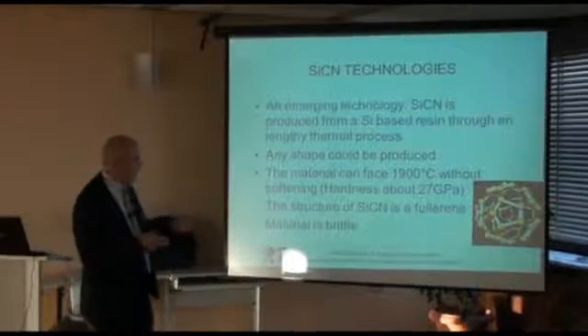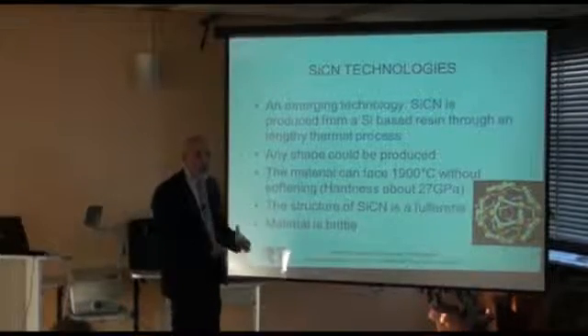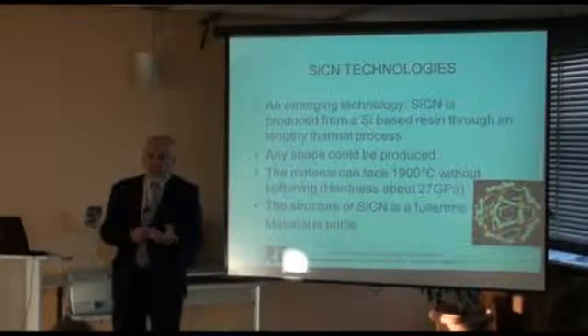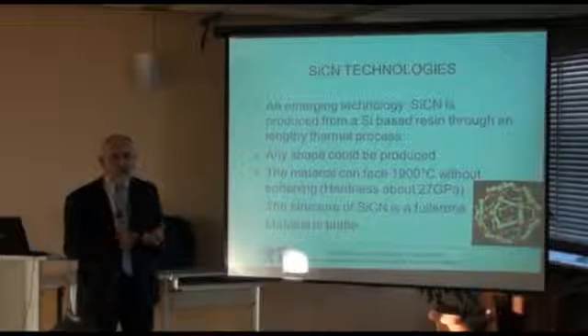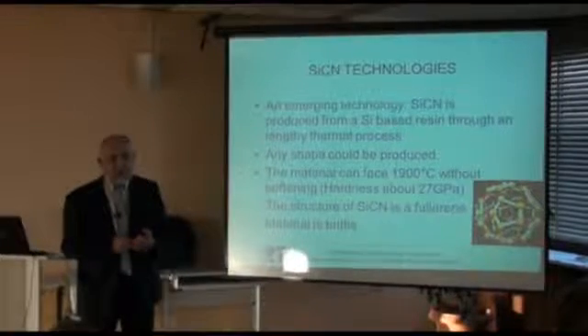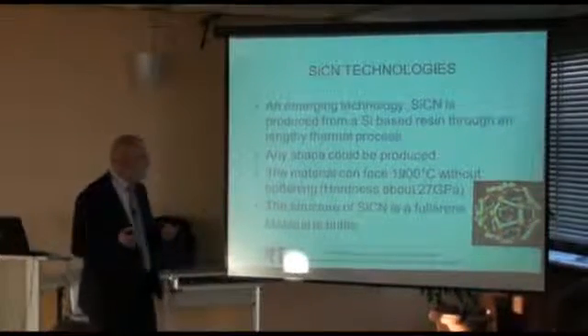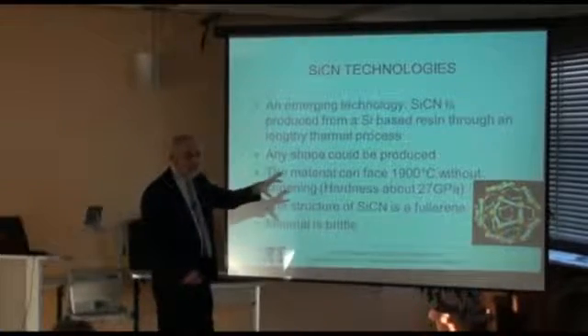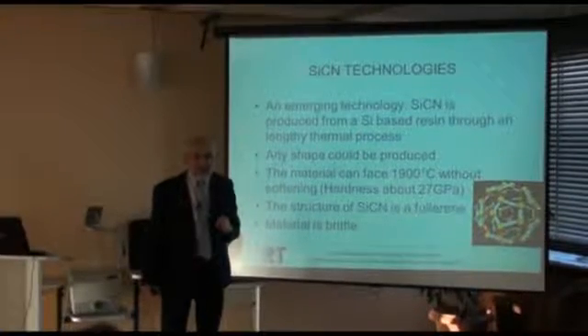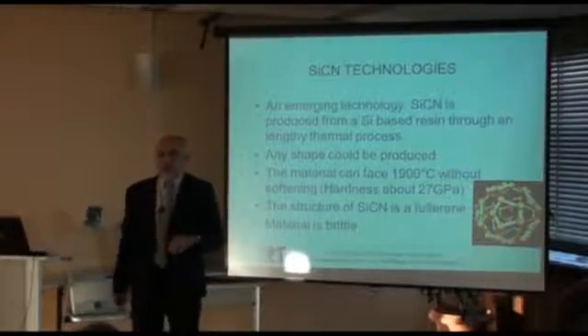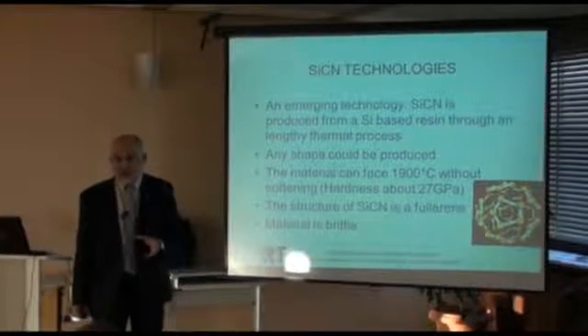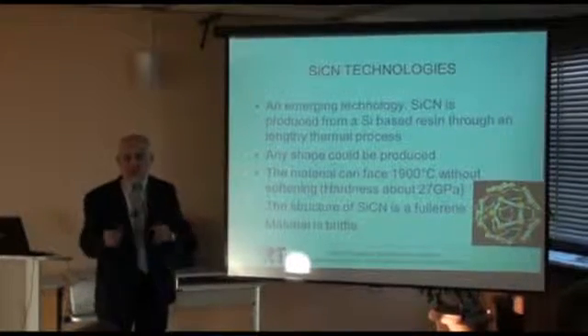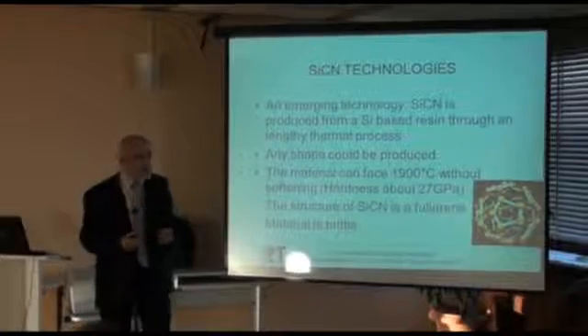That works fine. There is a process following that of pyrolysis. I mean, it's cross-linking and pyrolysis, and that means heating without oxygen. And I get a ceramic. The point is that the ceramic shrinks about 30%. And I say about because you don't know exactly how much. Every time the batch is different from the polymer, you get a different number.